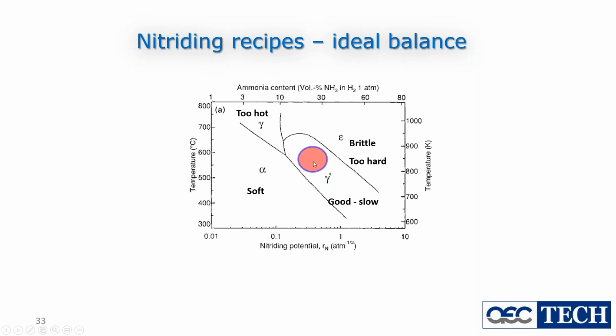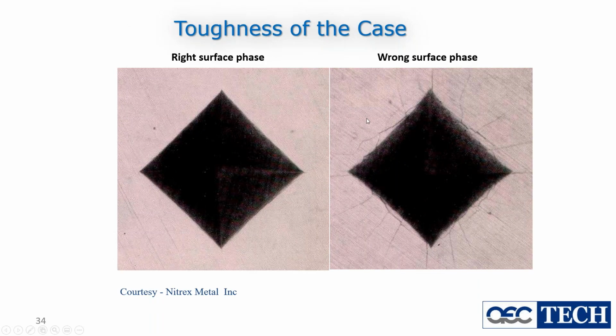Why is this so important? If we make a brittle phase at the surface, if we get gamma and epsilon instead of gamma prime, this is what happens. One of those hardness indenters has made a pyramid, and you can see that pyramid has been driven into the surface to calculate the hardness. These two hardnesses are very similar, so the pyramids are the same size. But on the left-hand side, there's no cracking, and on the right-hand side, there's cracking when you drive the pyramid in. And you actually sometimes see this when you're doing tests on these surfaces.